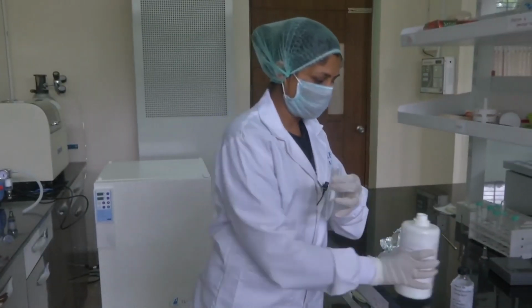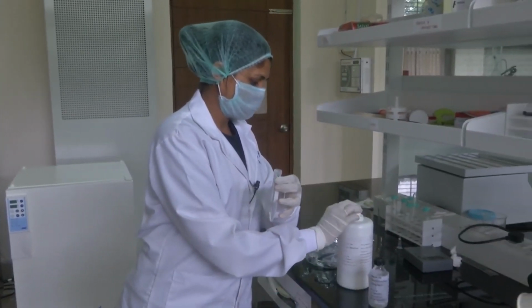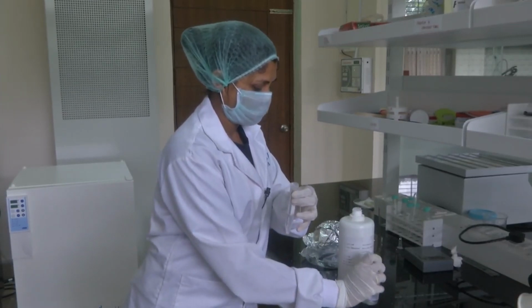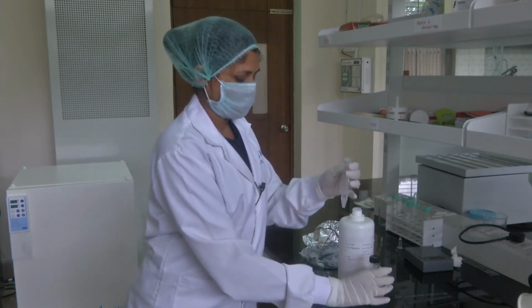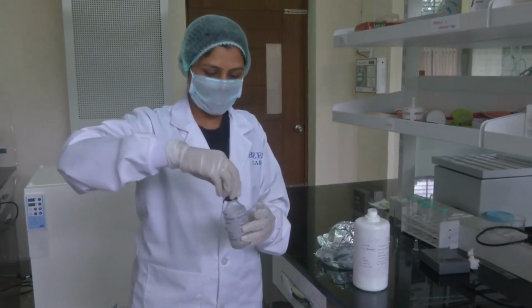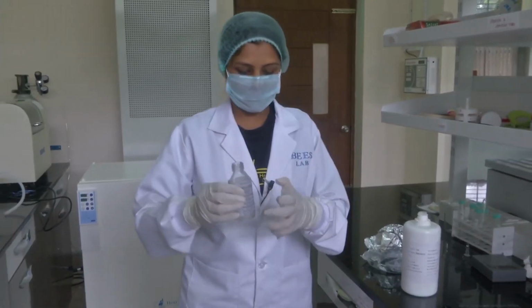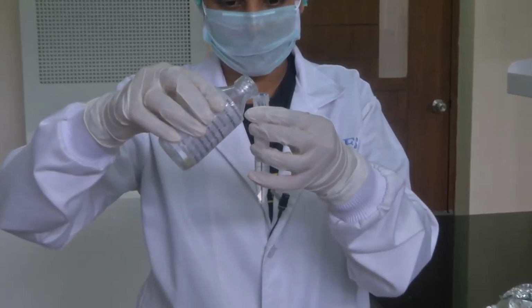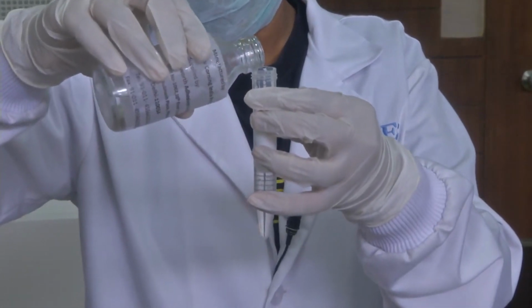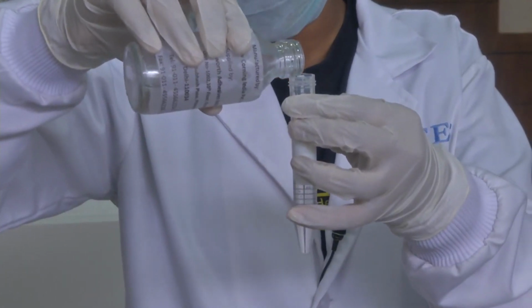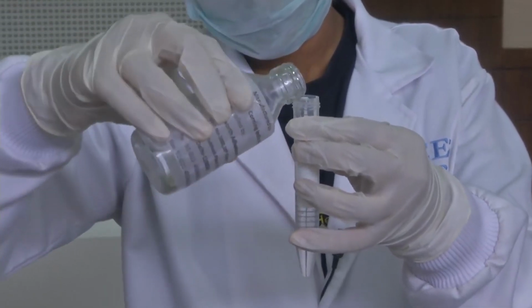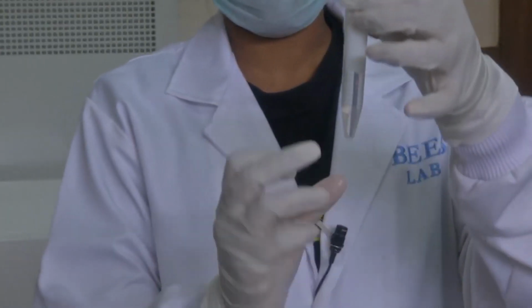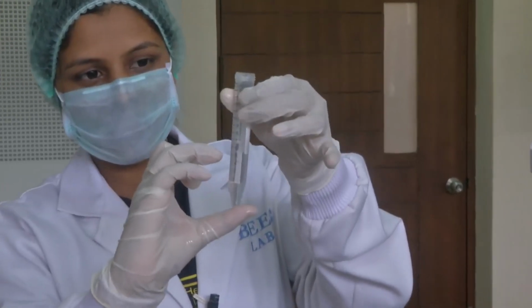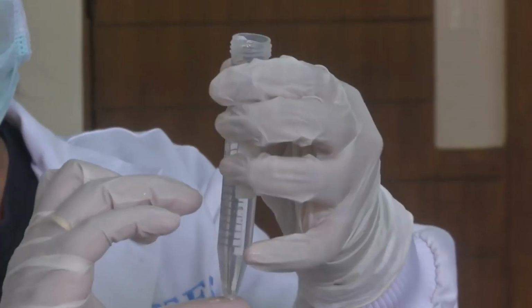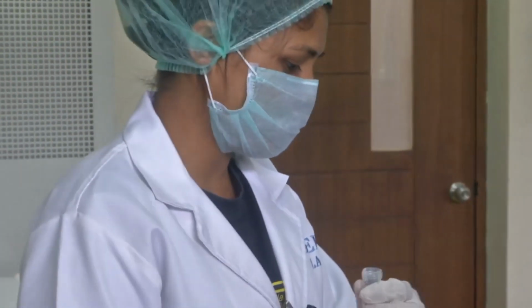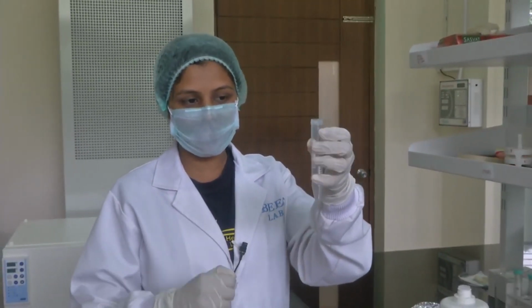Now that I have taken some amount of elastomer, now I take the curing agent. So, I need to take 0.5 ml of curing agent. Now, if you see, they are viscous. As you see, the curing agent would be floating on top, and then at the bottom I have the PDMS, the silicone elastomer. Now what we have to do is stir this well.